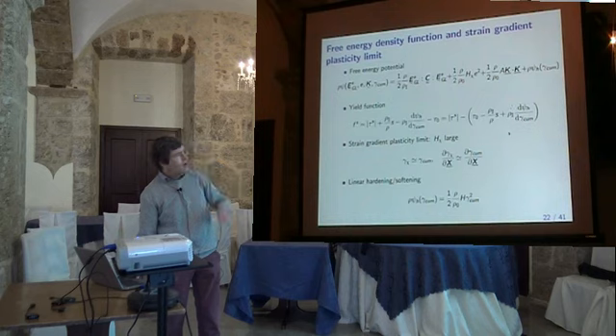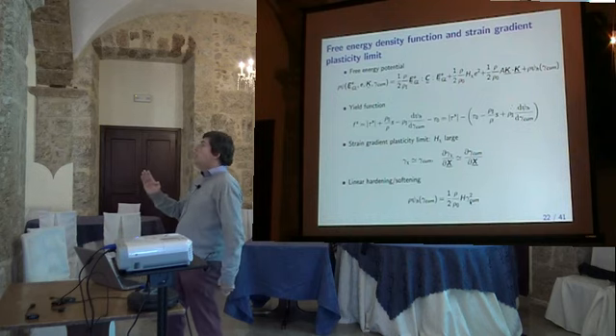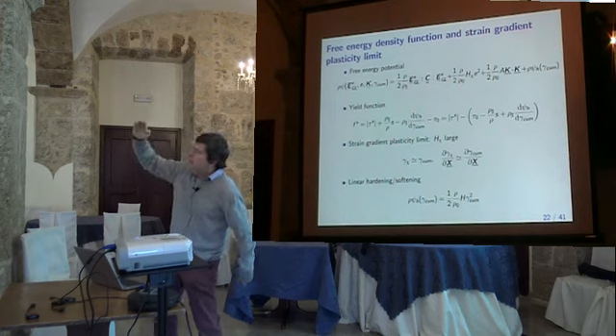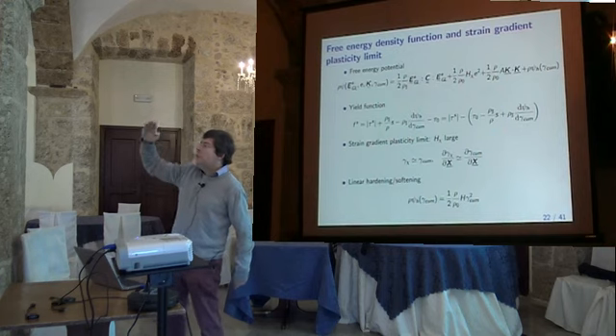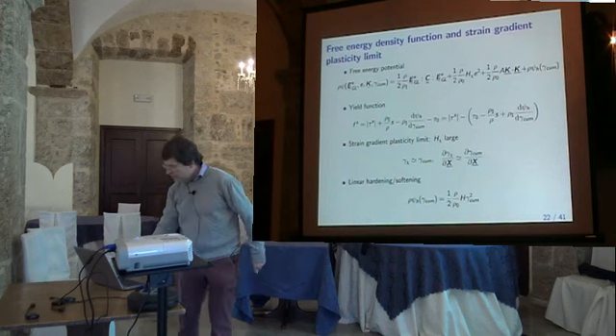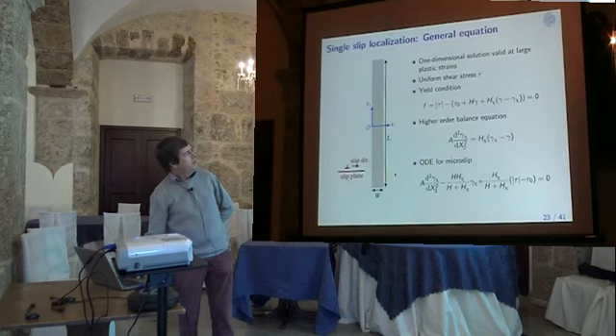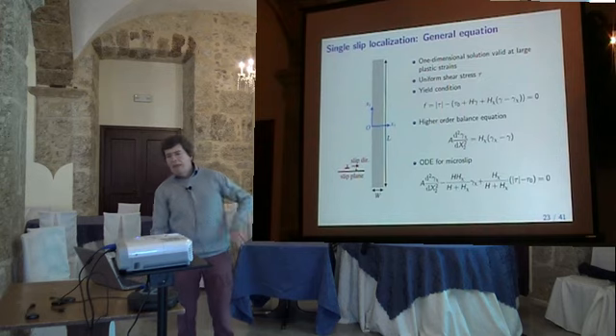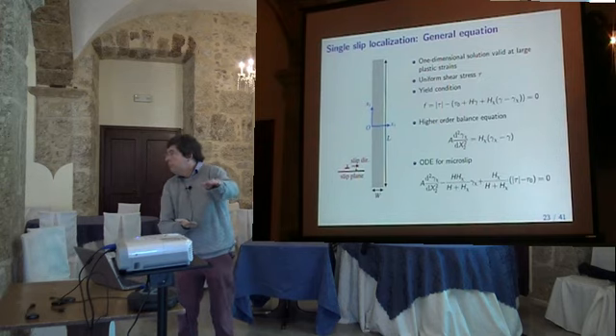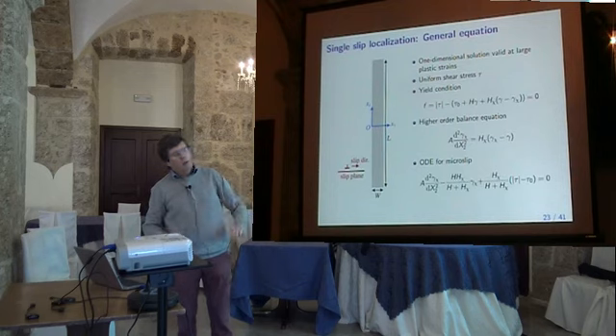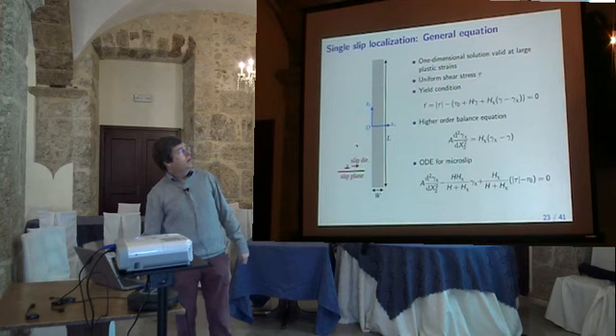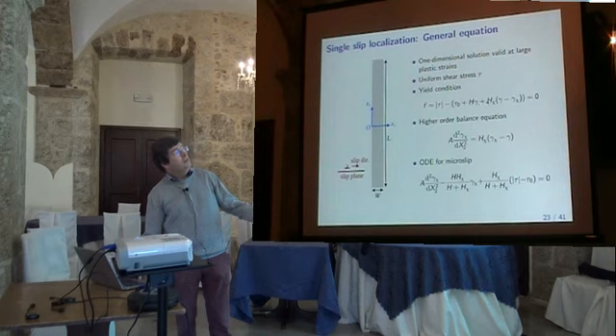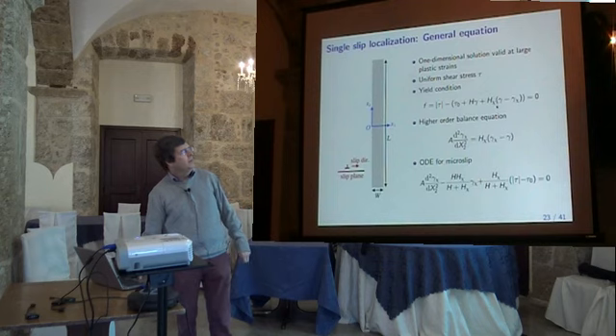So let's take a quadratic potential for the hardening. It means linear hardening. So you're elastic, and then you have linear hardening. H can be positive or can be negative. And we will study all these cases. So we consider simply a slip plane like that. We apply periodic slip like this. And we will look at the effect of boundary conditions also on that, and we will consider this simple linear hardening here. This is in fact the Laplace term which is hidden here by this micromorphic equation.